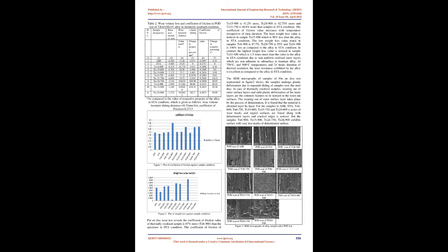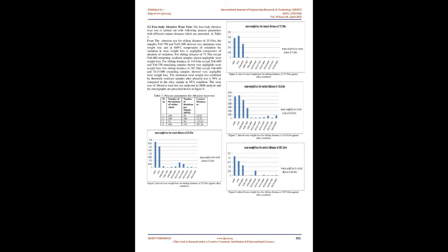The thermally oxidized samples are subjected to friction and wear test on a Ducom pin-on-disc apparatus under dry sliding conditions as per ASTM standard G99-95a. The pin-on-disc apparatus has a steel disc with hardness of 63 HRC, and the load applied for the test is 2 kgf, 19.62 N. The track radius and speed of rotation of the disc are 60 mm and 400 rpm respectively.